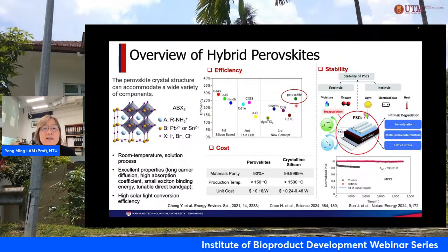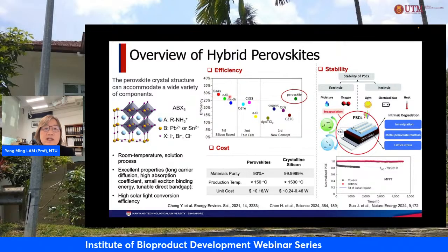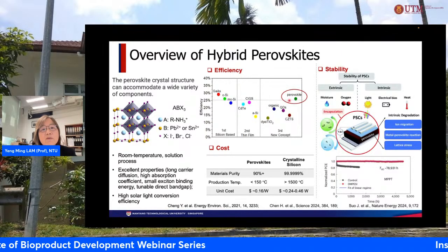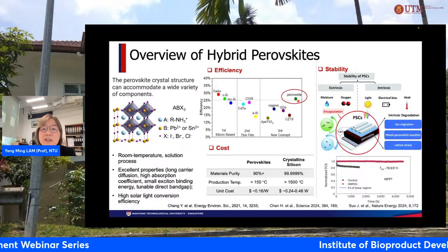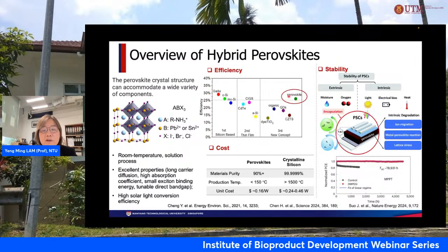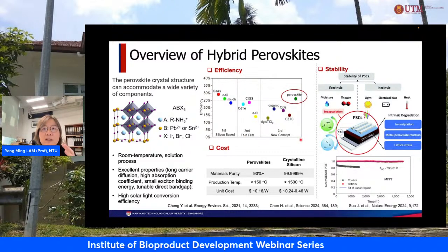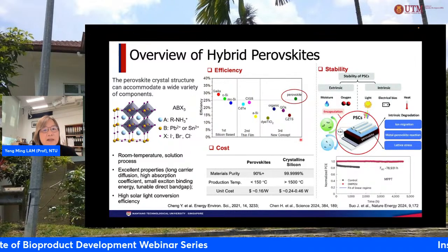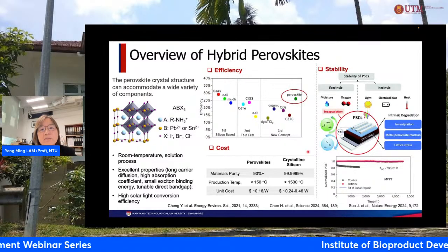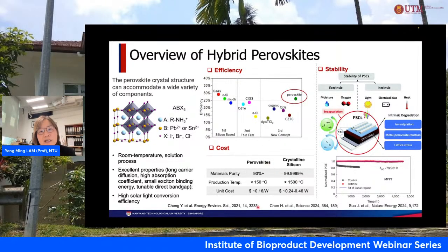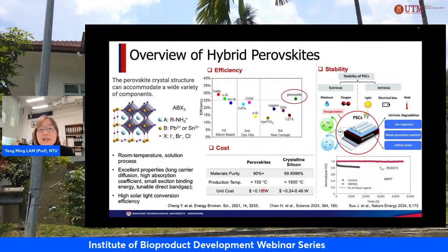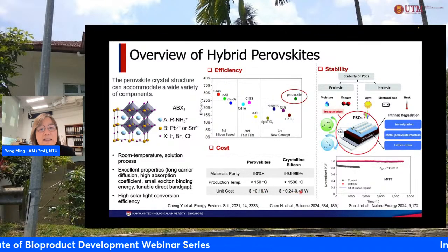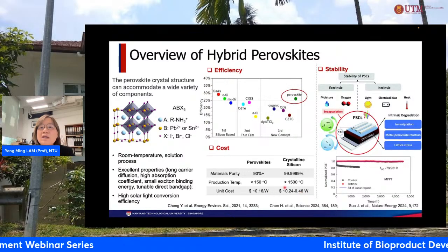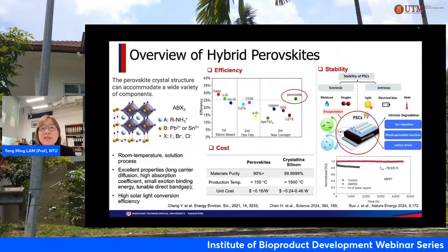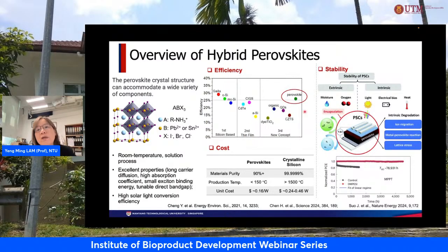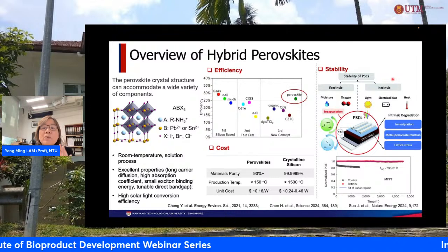If you compare perovskite to conventional silicon solar cells, the efficiencies are very comparable. Currently the best perovskite solar cells run at about 27% efficiency, so it's now competing very closely with silicon. But I have to say, silicon has application areas which are very difficult to replace. In any case, if you look at the cost of perovskite, the current per-unit cost is 16 cents compared to 24 to 46 cents for crystalline silicon. So the cost comparison is also very strong. The problem with this material is that there's great efficiency and a great cost ratio, but stability is one consideration that most people are concerned about.